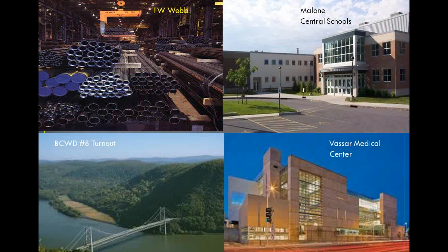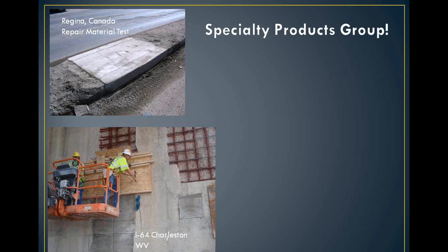On the upper left is kind of an interesting project. That's FW Webb here in New England. They're building 63 large-scale plumbing supply warehouses with a front-end showroom, and they used VaporLock in all their concrete. They didn't have to put a material on top there to stop dusting in their warehouse because there is no dusting when you use VaporLock. They polished the showroom floor. They went much faster because VaporLock had already done much of the densification that's necessary in the polishing process.